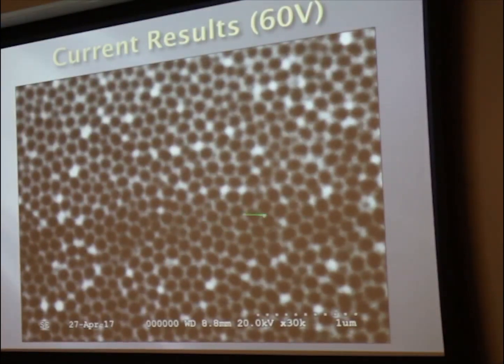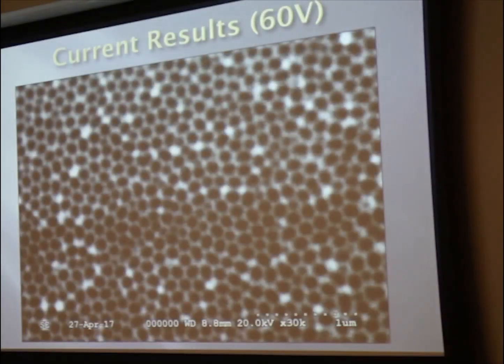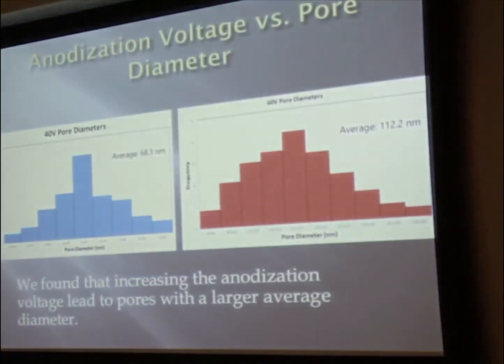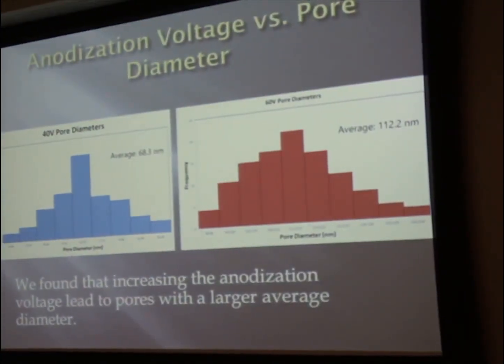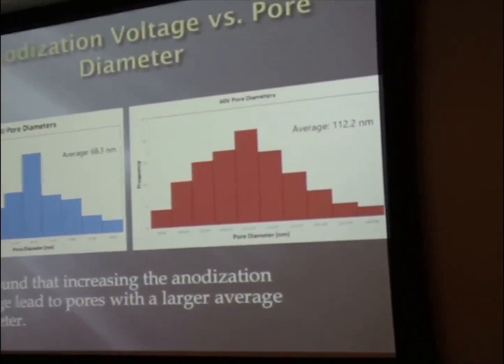So if you take a look at the 60-volt sample, you have a similar ordering. If you look at one of the pores, there's going to be 6 of them around it, but the pores are much larger in comparison to the 40-volt. So we want to see, okay, they definitely look bigger, but how much bigger? We can use image processing and the SEM to actually find the pore diameters.